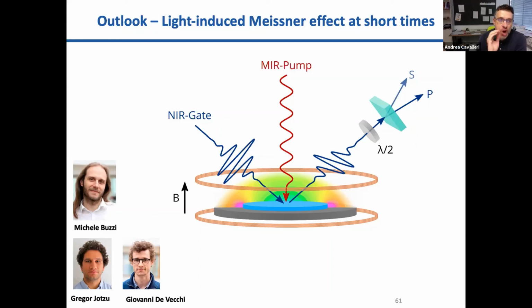the answer to which is no, because the material is a metal and I am exciting at the surface. But it's a very interesting question for at least two reasons. Firstly, I do think that when the material is being driven by long pulses, what I'm really doing is enhancing the correlation length of the superconducting state, perhaps to sizes that are far larger than that of a vortex, and thereby making the state metastable rather than just disappearing immediately.